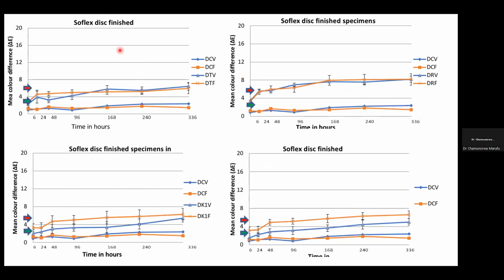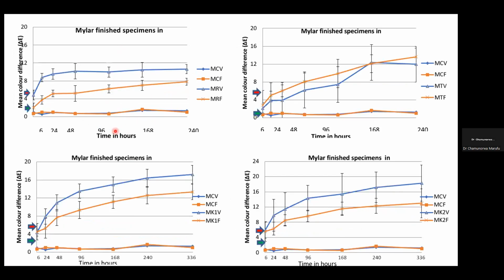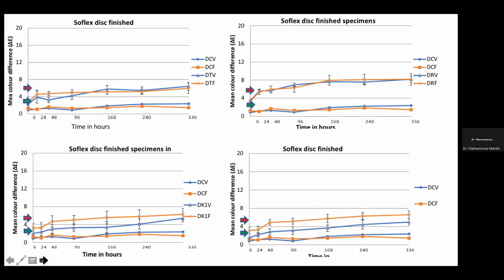The second group, this was finished using Soflex disc. So you can note that obviously the color change in this group is way lower than what we saw in the previous slide, where we showed the results for the mylar finish. And also you can note that the variance, the error bar, the standard deviation is way less in all the experimental groups. The color difference was comparable, as in there was no statistically significant difference between the nanohybrid and the nanofil and the microhybrid when they were finished with Soflex disc. And also they were way more color stable compared to the scenario with the mylar finish.